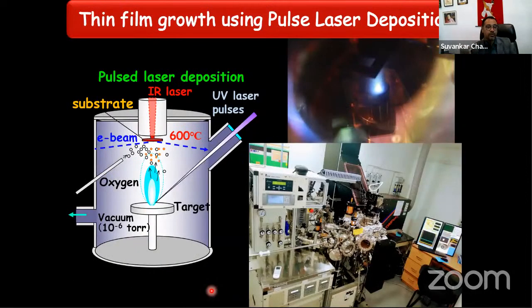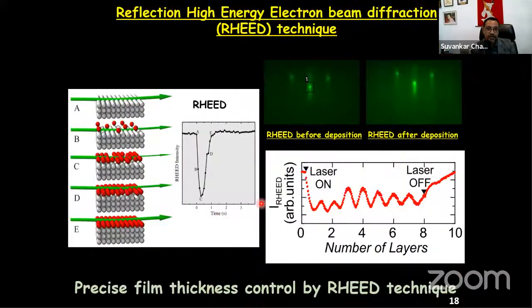So we are using what is known as a pulsed laser deposition system to prepare our sample. This is a picture of our pulsed laser deposition system, and our system is equipped with what is known as a reflection high energy electron diffraction system. It's a very unique system: you look at the diffraction pattern of the electrons, and by counting the oscillations in the diffraction pattern when you start depositing, you can figure out exactly how many monolayers of the thin film you have grown on top of your substrate.